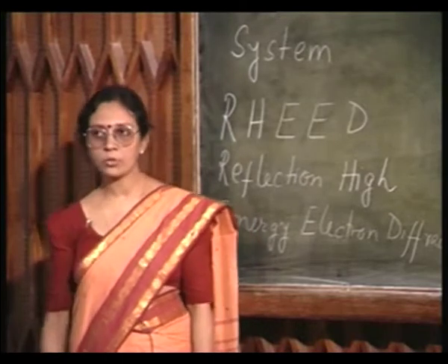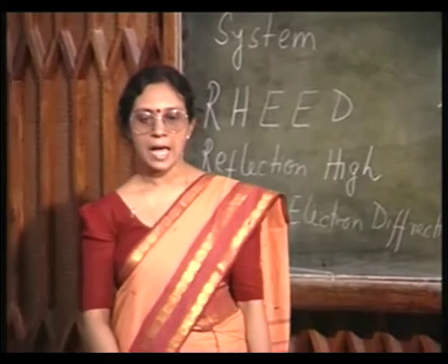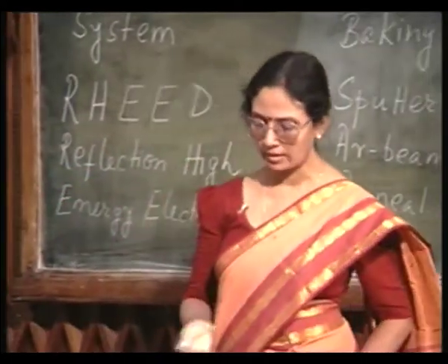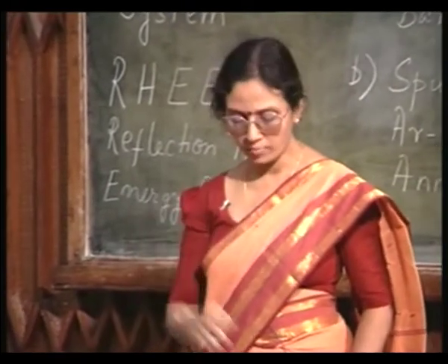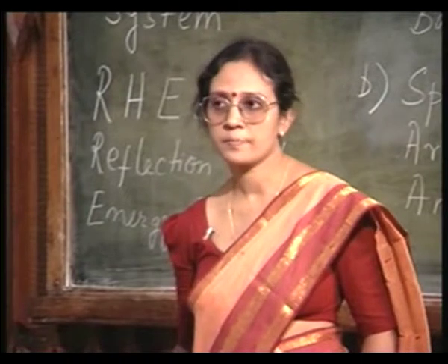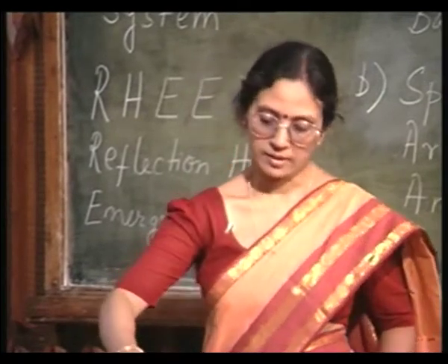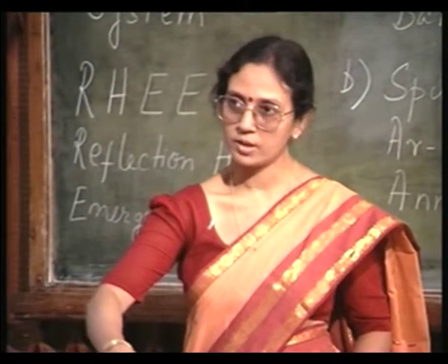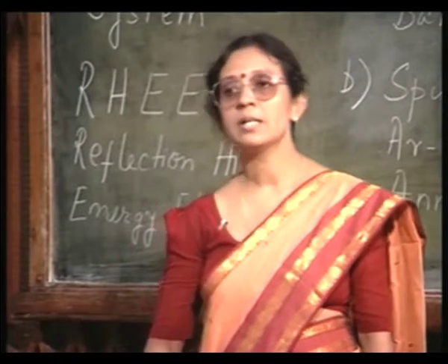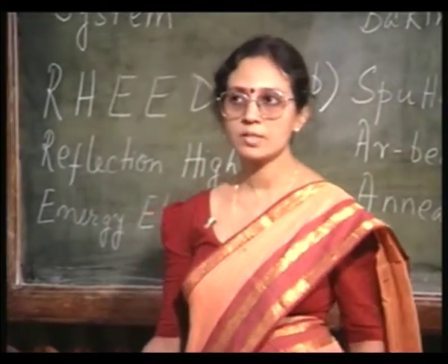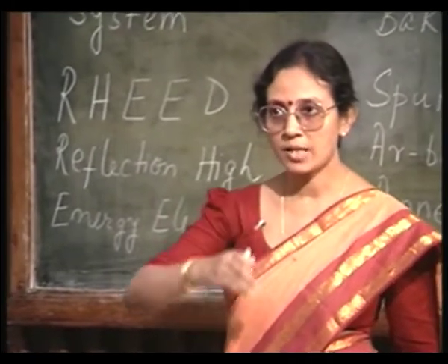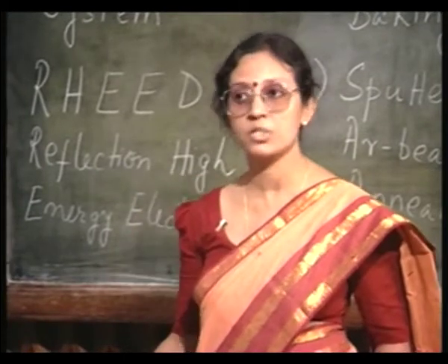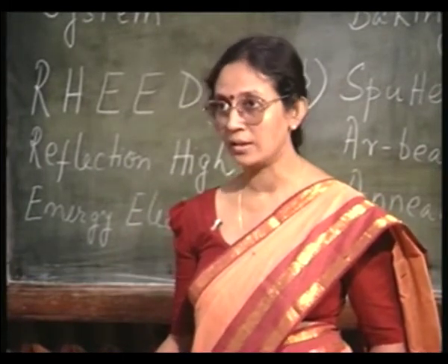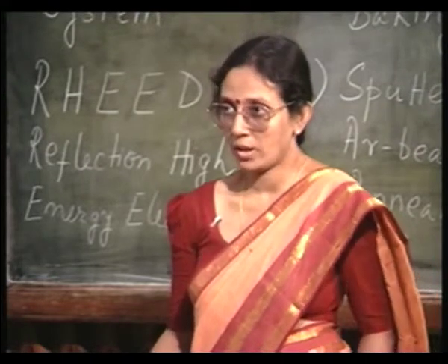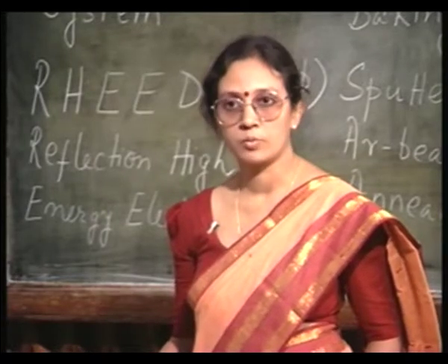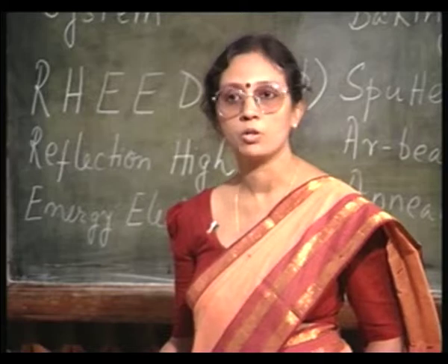So, what you do is you focus an electron beam at a grazing angle, very small angle, about 1 degree or so. Focus an electron beam, 5 to 40 kilo electron volt energy, focus it in a grazing angle like this. If this is your substrate, focus it like this at a very small grazing angle, so that the penetration depth will be very small. So, what you are measuring is actually the surface quality. As the epitaxial layer is growing, you are measuring the surface quality in situ, and looking at the RHEED pattern, the diffraction pattern, you can assess how the crystal quality is going to be, whether it conforms to your requirement or not.